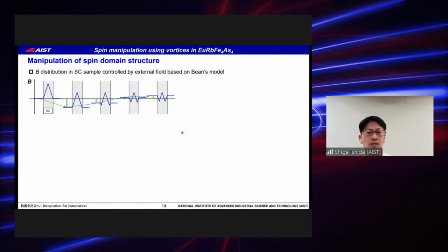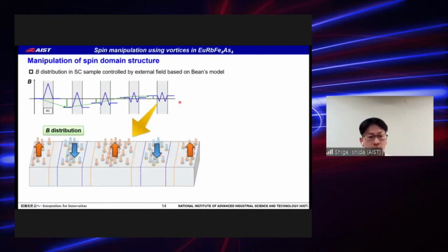Then we conducted an experiment to test the possibility of spin manipulation using vortices. As explained previously, the B profile inside the superconductor depends on the process of applying the magnetic field. Here we consider first decreasing the magnetic field from a large positive field to a slightly negative field, and then increasing the field. The B distribution in the sample is expected to be as shown in this schematic diagram.